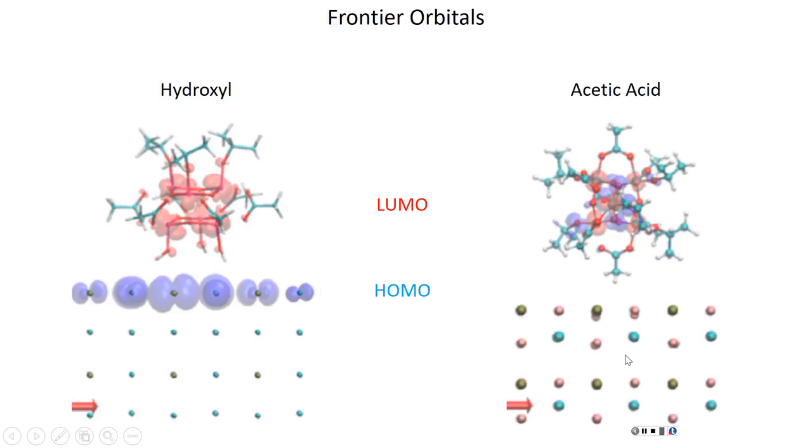So the offset determines whether this configuration will ever be able to participate in charge transfer, because the rightmost acetic acid doesn't show charge transfer at all at the lowest state. And second, the height of a barrier, or just the rate of the photoinduced charge transfer, is how ligands, or the amount of vacuum between donor and acceptor, affects whether the charge transfer will be quick enough.